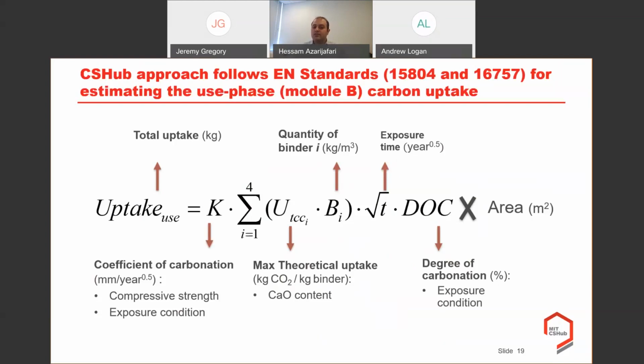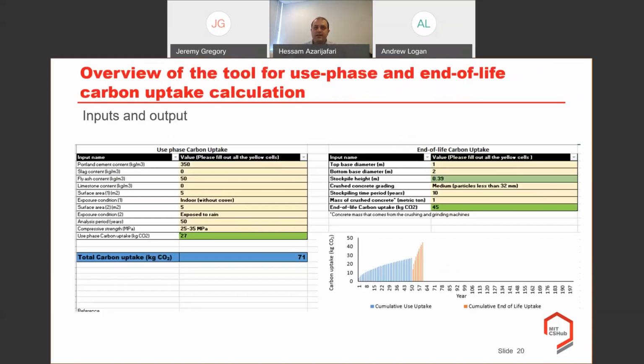As we talked about, the relative humidity. In low relative humidity, we have some difficulties with the carbonation, and in high relative humidity, we have the same thing. And all these values that will give us the kilogram CO2 per square meter area of concrete will be multiplied by the total area, which will give us the total kilogram CO2 captured during the use phase of the concrete.